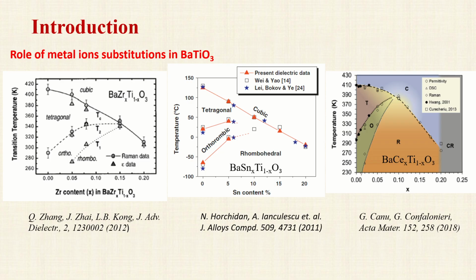When increasing the substitution degree with metal ions, we observe an increase of the transition temperatures for rhombohedral to orthorhombic and orthorhombic to tetragonal phase transition, and a reduction of the tetragonal to cubic phase transition. In addition, the phase diagrams show that there is a region in which all four phases might coexist. That is a quadruple point.